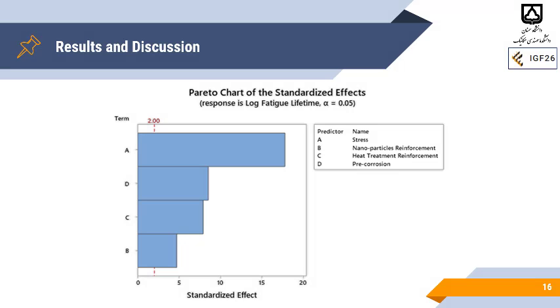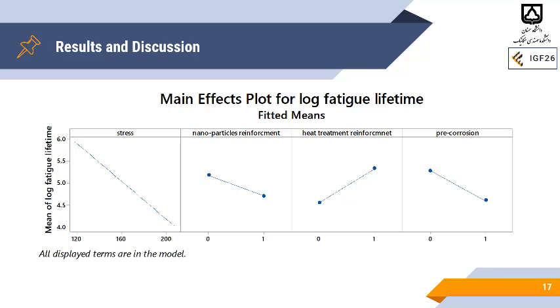From the Pareto chart you can see A is the most important parameter affecting the output on the logarithmic scale of the fatigue lifetime, which is stress. Then D is important, which is pre-corrosion, then the heat treatment, and the last parameter which is also effective is nanoparticle reinforcement. If you check the trending behavior of each input on the output, you can see, as expected, that by increasing the stress, the fatigue lifetime decreases. By nanoparticle, that is an interesting result: with nanoparticle you have lower fatigue lifetime, but with heat treatment you have higher, and as expected pre-corrosion leads to lower fatigue lifetime.